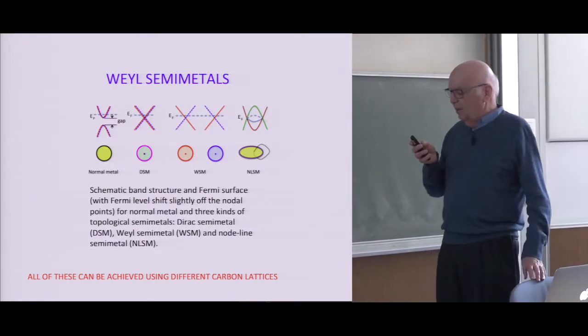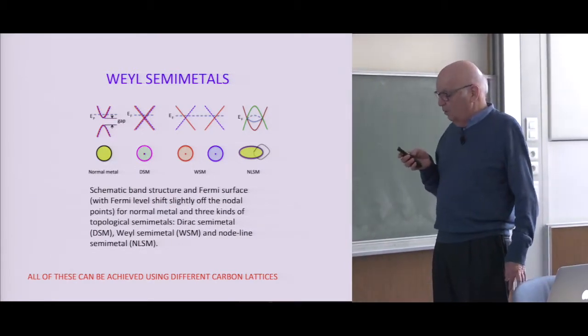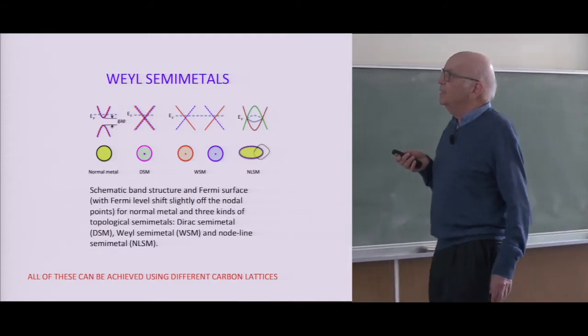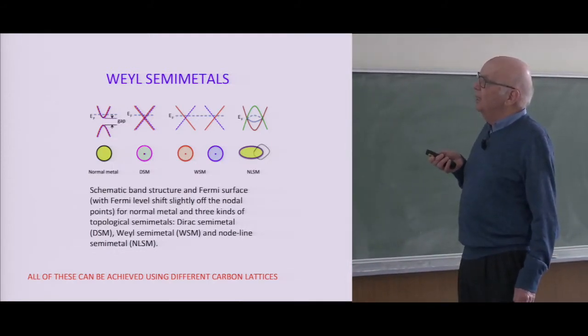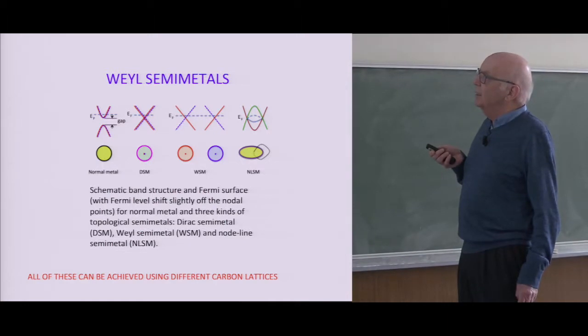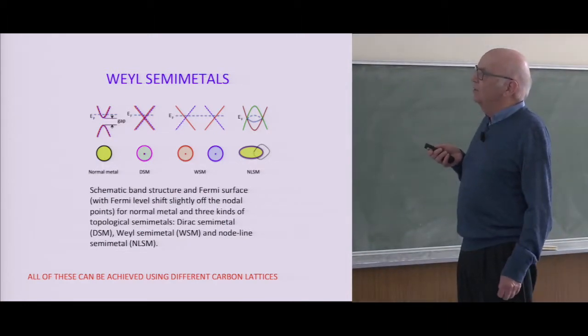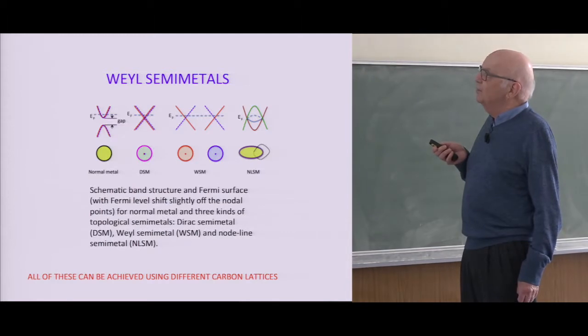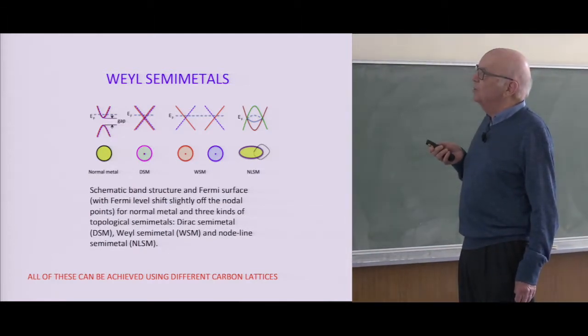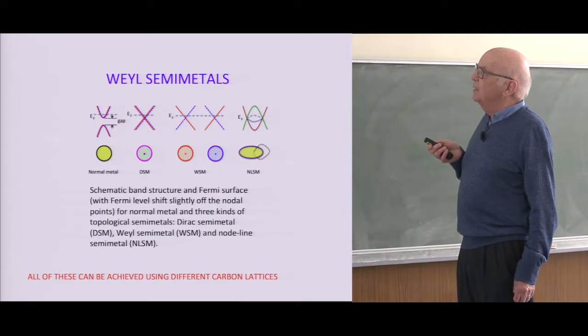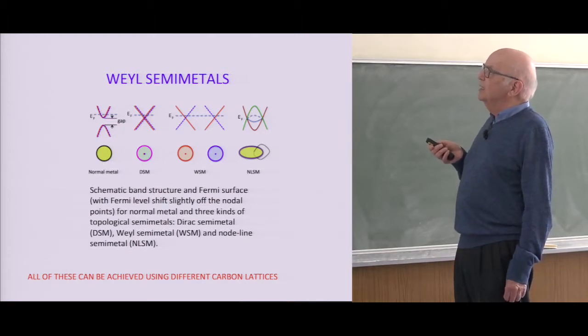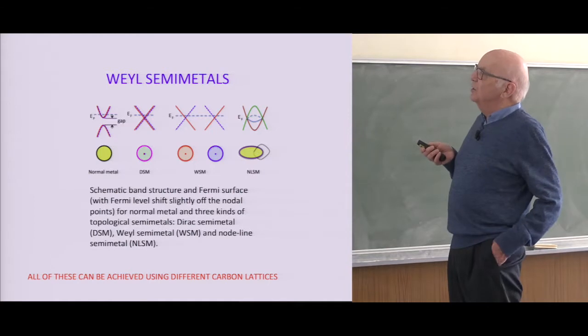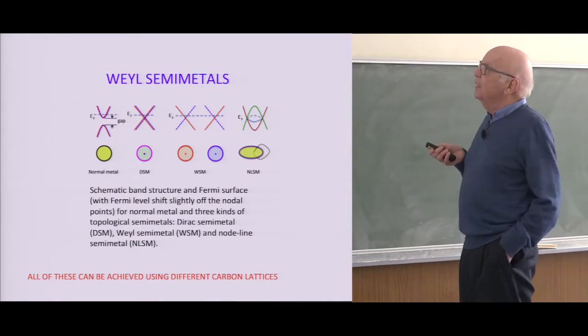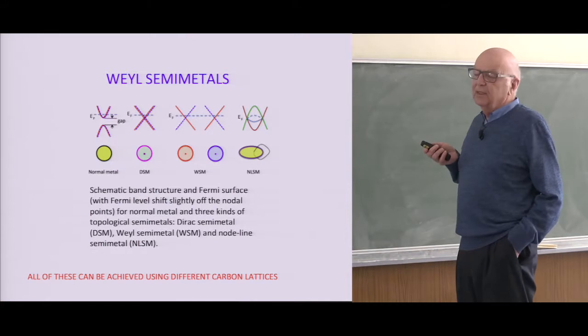Another thing that's popular now is to work on Weyl semimetals, and I'll just tell you what that is. Here is a normal metal, where you have a valence band, a conduction band, and a gap. Here's a Dirac semimetal, where you have graphene, with linear dispersion and no gap, and the Fermi level would be here, so you get something that's different. If you have two parts of the band structure connected in this way, you can show that this is a Weyl semimetal and has interesting properties.